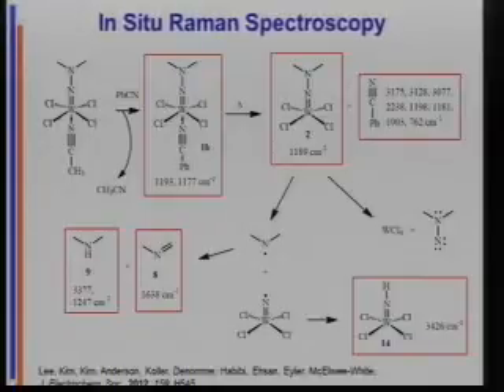Okay. And this peak at 3426 is when that radical abstracts a hydrogen from the methyl here. That gives you another equivalent of that and one of these. So we're seeing experimental evidence for that homolytic pathway that we had proposed. And by the way, you can do this with the isopropyl compound, and you see propene. Exactly the same. The isopropyl stuff isn't published yet. We're writing it up now. So this all works. All right.